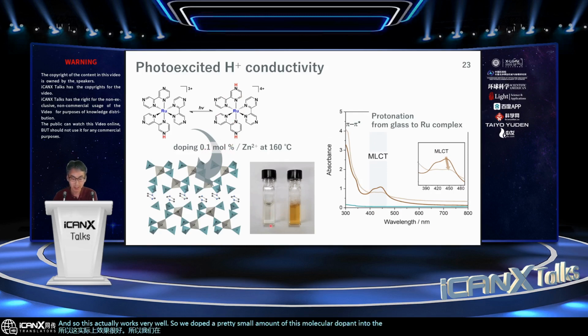And you can see that this cuvette sample, this is a glass before the doping and after the doping. Even in the very small doping, it has a color. It is transparent, but a slightly yellowish color. And after making this doped glass, we measured the absorption, which shows the obvious change of the metal ligand charge transfer. So this means inside of this glass, this ruthenium complex gets the proton from this proton conductive glass.